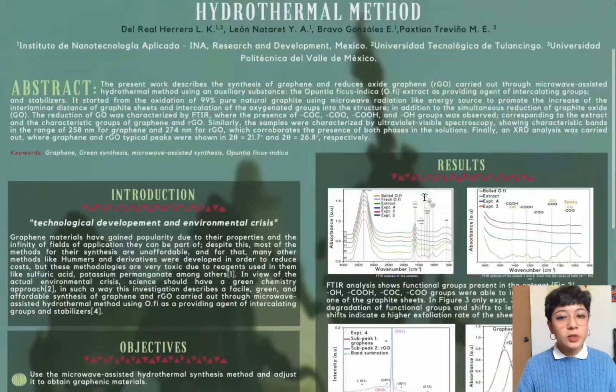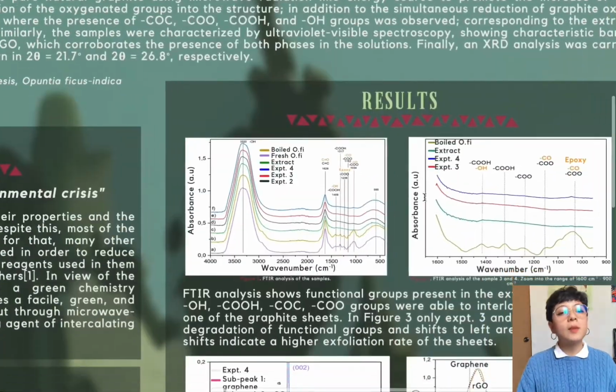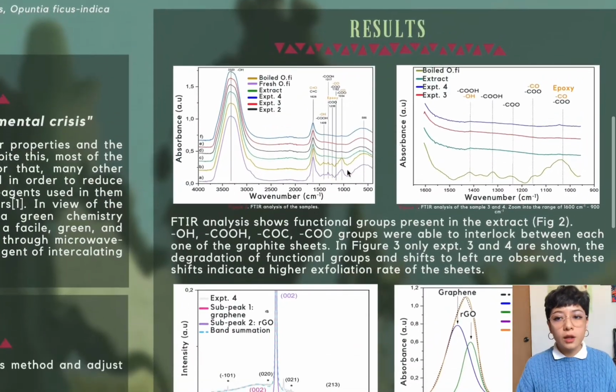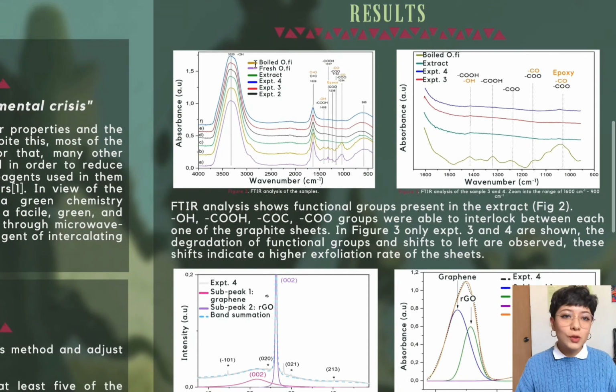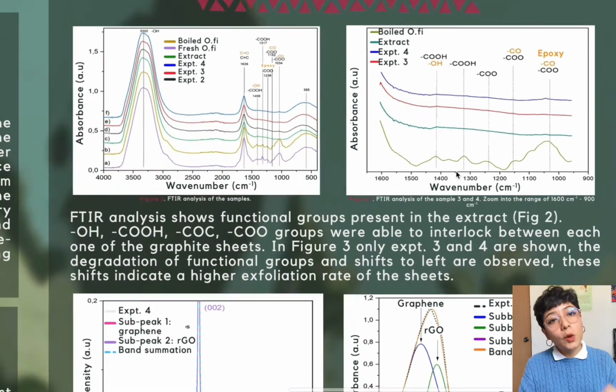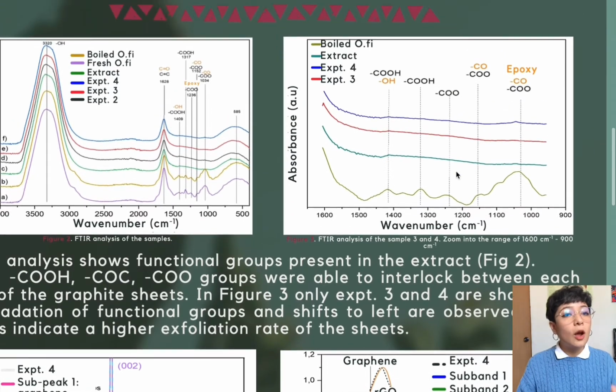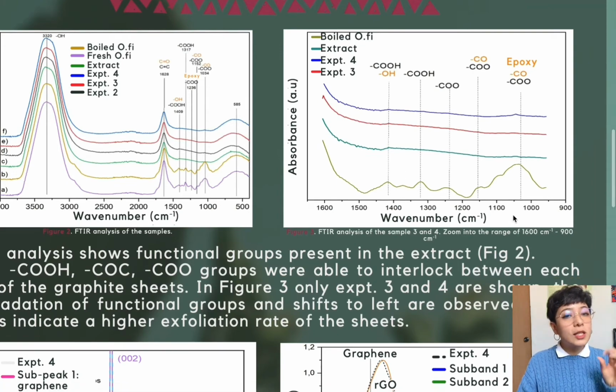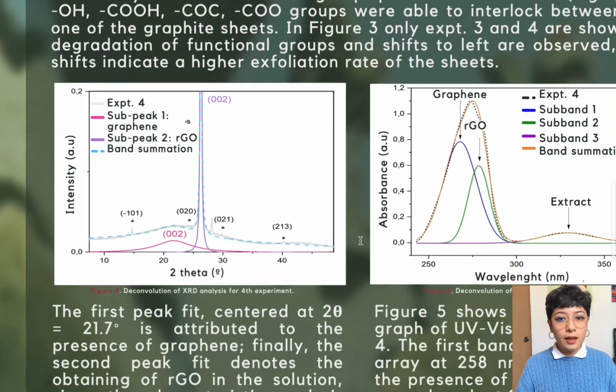Okay, now let's go with the results. The samples were analyzed by different techniques. First, FTIR analysis. In figure 2, the analysis showed the functional groups as carboxyl, hydroxyl, ketones, epoxy, etc. present in all the solutions. Now, in figure 3, we're gonna make a little zoom on the fingerprint of the samples. We can see to the naked eye the high rate of degradation of the functional groups and shifts to the left, which means a higher exfoliation rate of the sheets.